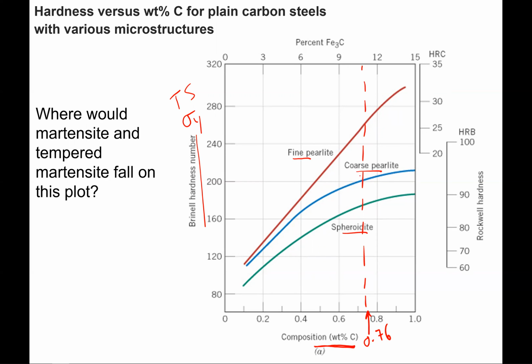And so we have a coarse pearlite and a fine pearlite. You can see the finer structure of the pearlite. The more layers we have, the closer the layers are together, the more resistant to dislocation motion, and the higher the strengths. And then spheroidite, again, we're going to do that in a minute, is going to be the weakest of the structures and very high ductility. So spheroidite might be useful for forming the material into a different shape, but it's not very useful in itself because it's too weak, and so you then have to reprocess to form a new microstructure.